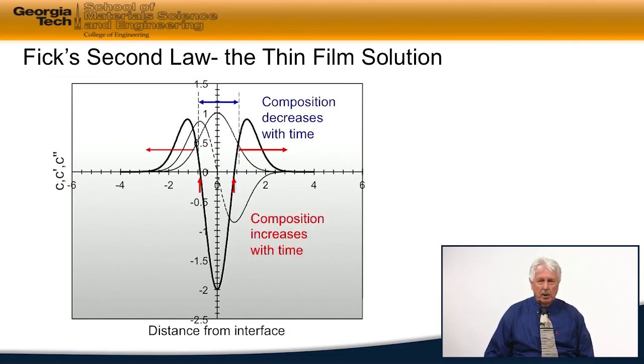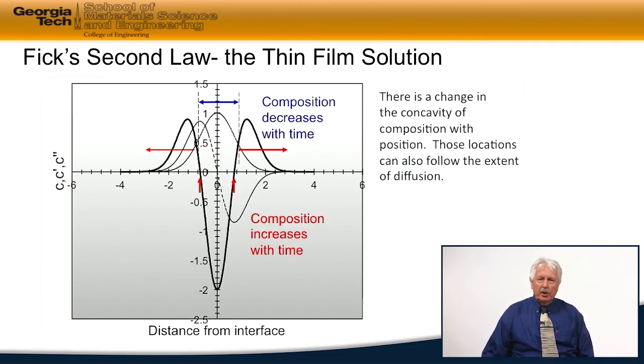Now, if we go back with respect to examining Fick's second law and we think about it in terms of the concavity of the composition function, what we see is, here's Fick's equation, and when the concavity is negative, we're seeing that the composition is decreasing with time.